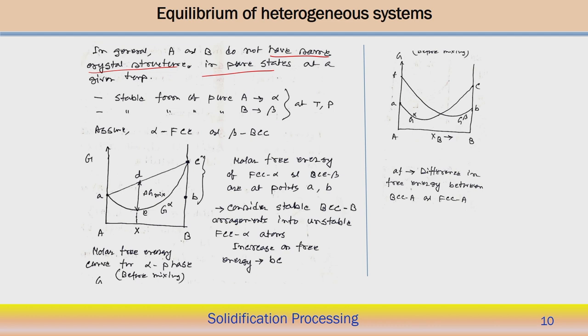For example, the stable form of pure element A is the alpha phase (FCC structure) and the stable form of pure B is the beta phase (BCC structure) at a particular temperature and pressure. In this heterogeneous system, we draw the Gibbs free energy curve. The molar free energy curve for the FCC alpha phase — with alpha as the stable FCC structure — and BCC beta are the points A and B respectively.